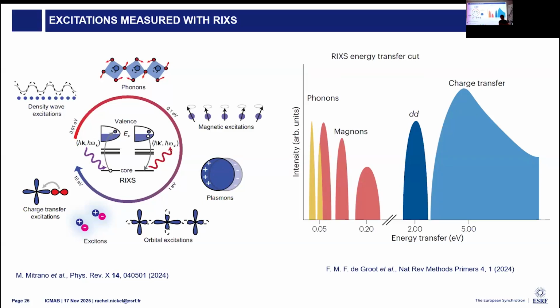The excitations that we measure depend on the energy scale that we're looking at, and it depends on the resolution of the instrument. So with our high resolution instrument, where we can measure in the tens of meV, we're sensitive to some phonons, magnons, and bimagnons. So this will be stretching from about 20 to 30 meV up to 200. We can also measure the dd, so these are the orbital excitations, which are in the 1 eV to 2 eV range, and then charge transfer features. Which excitations you're interested in will dictate which instrument you want to use and will really demand what resolution you need.